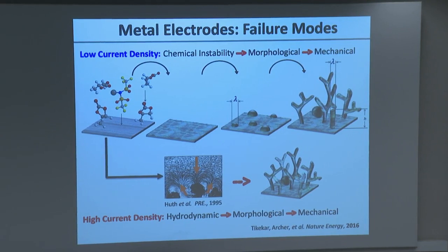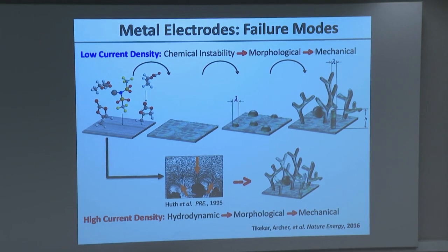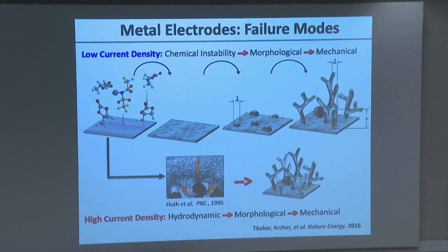Remember, no one knows this, right? So don't get carried away. People just believe this is what occurs. And these heterogeneous interfaces, as you can see from the differences in color, are clearly different. They might have different thicknesses. They might have different transport properties. And so the thought is that the next step in this process is that the places along the surface that have faster lithium transport are better hosts for lithium. The end result is that when lithium deposits during the first cycle, it deposits in these bumps. And these bumps are called dendrite nucleates.